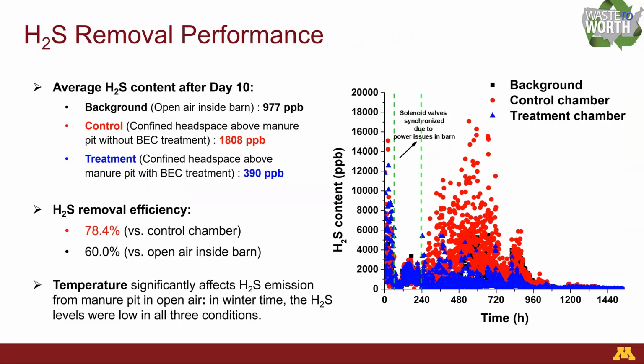The hydrogen sulfide removal performance: we can see the BEC treatment reduced almost 80% as compared to the control chamber without the electrodes. It also reduced 60% as compared to the ambient barn air. Another point I want to mention is that the temperature significantly affects the hydrogen sulfide emissions. When it's winter time, the activity of the microbes was quite low, which reduced the hydrogen sulfide emissions of all the conditions. But when it's summertime, the hydrogen sulfide levels need to be taken care of more significantly.